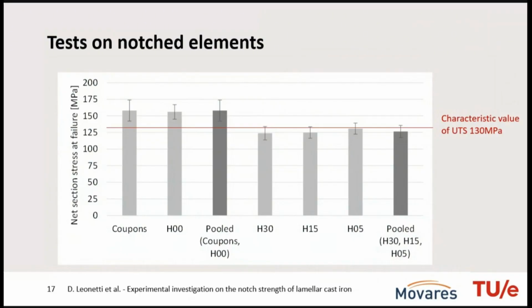But nevertheless, statistical significance is such that we can pool these two batches into one, and more or less we observe the same trend for the notched specimen. Apparently the severity of the notch in the linear elastic regime did not contribute so much to the strength. Actually, we see that for the specimens with a higher stress concentration factor, there is a slight upward trend, as if the gradient of the stress field could also be a driver for higher failure load. So higher gradient, slightly higher failure load, which is in line with what has been observed in the literature in bending, where they talk about an overstressed depth, as if locally the material in the presence of a gradient could exhibit stress higher than the ultimate tensile stress.